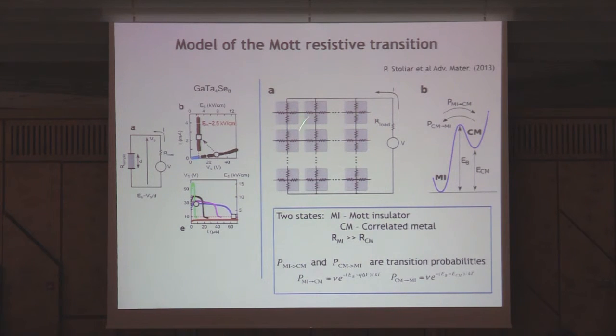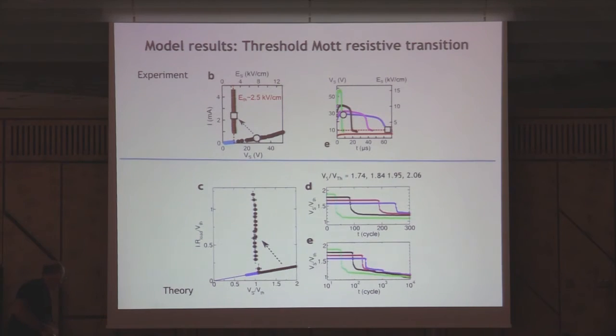So we start with a fully resistive lattice. We solve the Kirchhoff equations for our voltage protocol. We have the voltage drop at each cell. We compute the probability of going from the insulator to the metal. After each time step, we have a new lattice of resistors. We solve for that lattice all the voltages, and we compute the new probabilities, and we keep on doing that over and over through the length of our pulse. Clearly, it is embedded here that this system is volatile, because when there are no more pulses, all these things will relax back to the Mott insulating state. So this is what we wanted to capture, and this is the result of the simulations. So you see that you apply the voltage, you have a very well-defined threshold beyond which there is a transition.